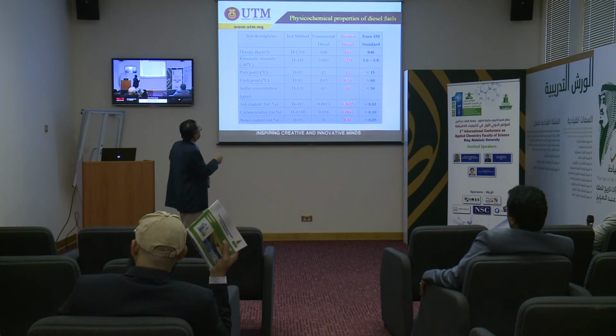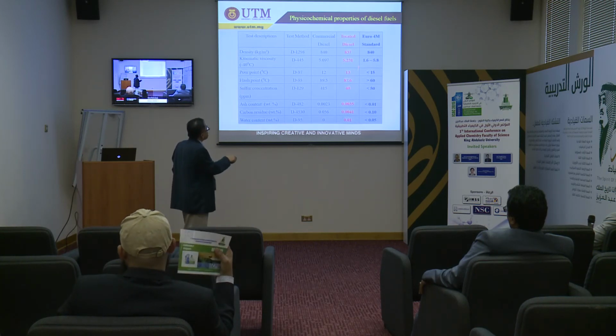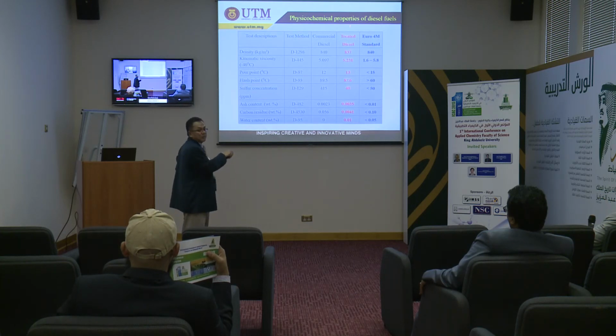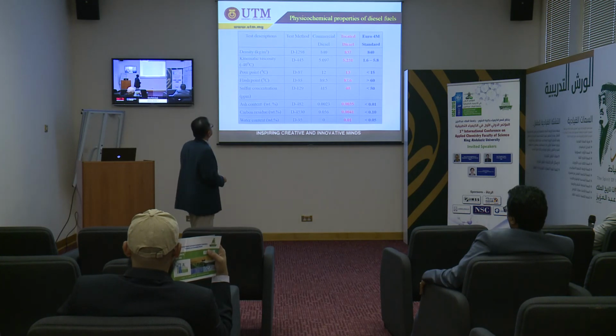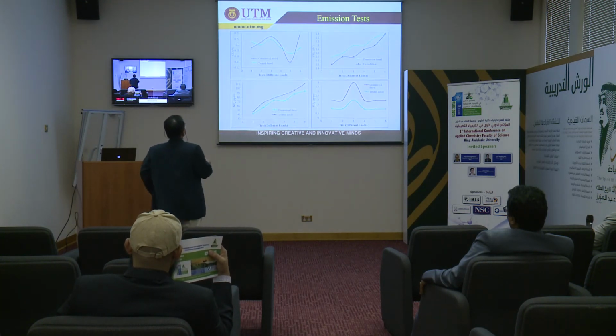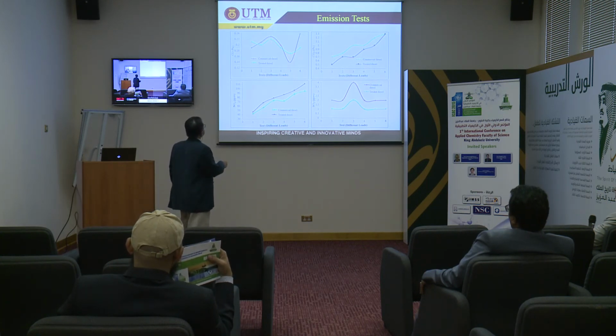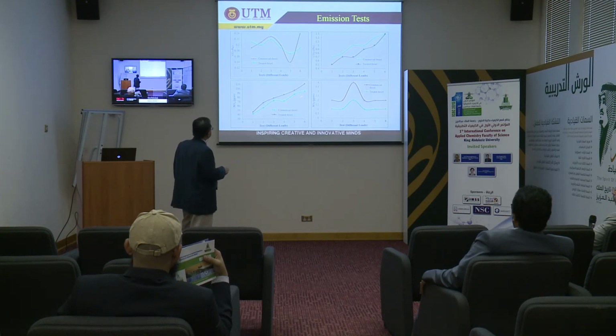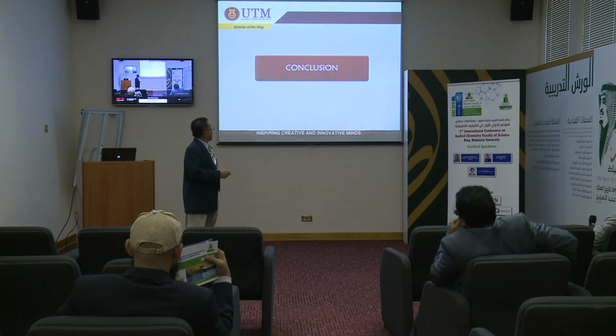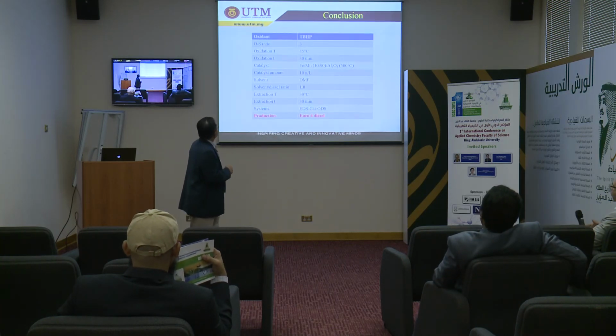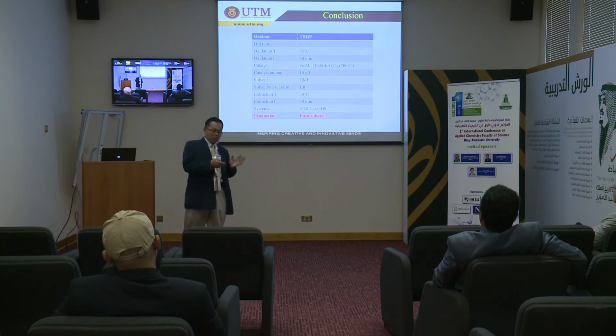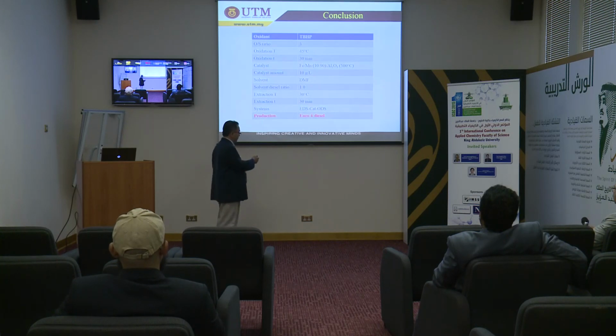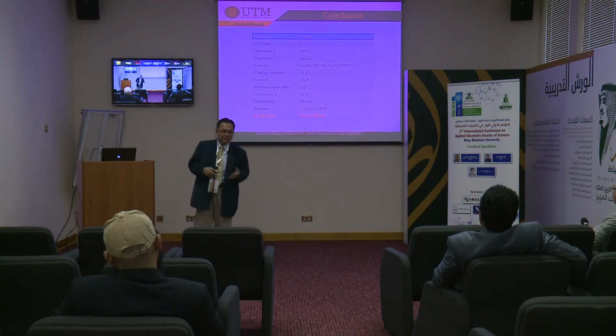This is the physical features of our treated fuel and the standard Euro 4. It is almost better, we found. I think this is a test we have done. With respect to CO, the treated one is much better. CO2, much better with the treated one, lower. And NOx, lower, and also SO2, lower. That's what we found. Okay, and this is the result. By using this technique, we hope that we can easily give Euro 4 in a cost-effective manner. I think that's all to share with you all.